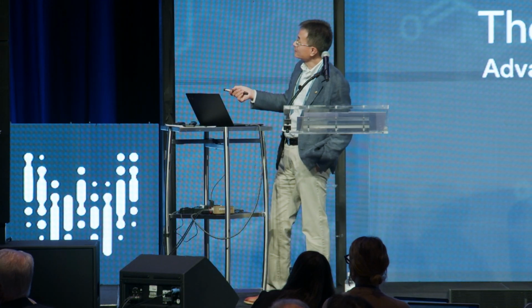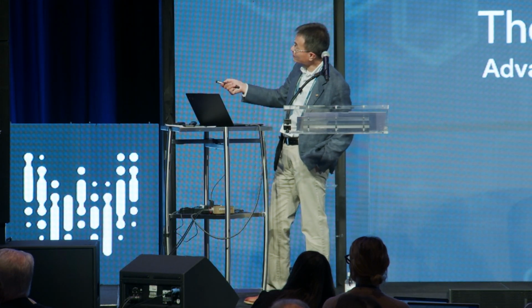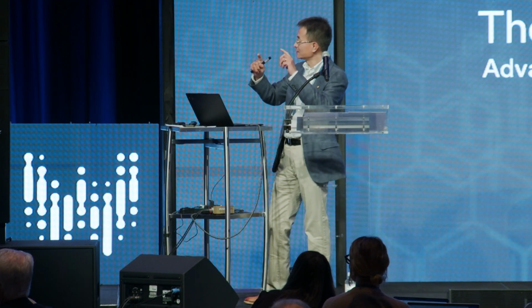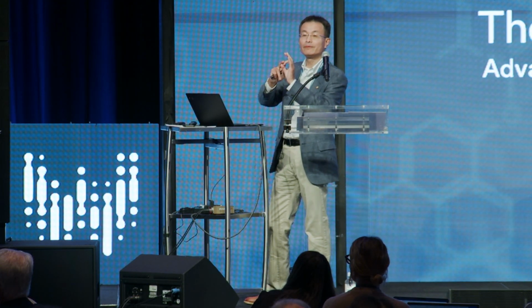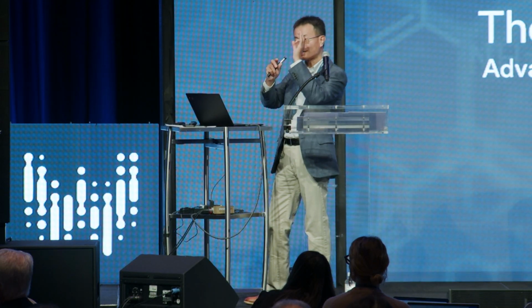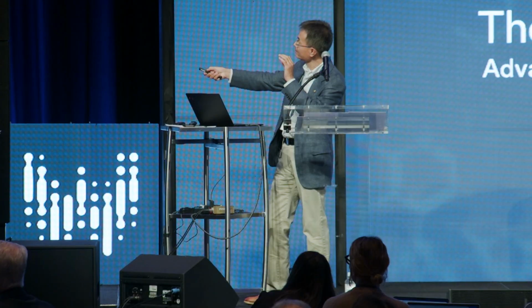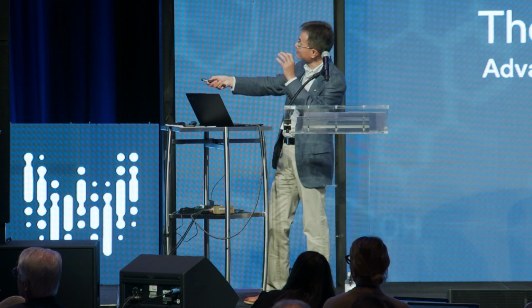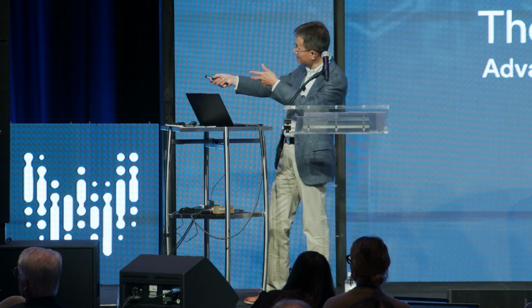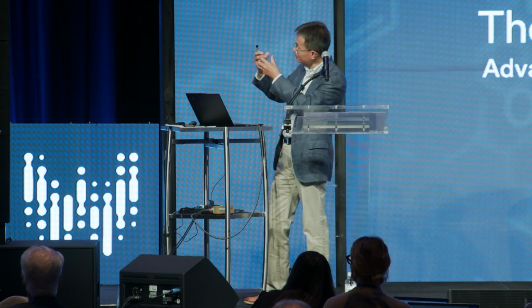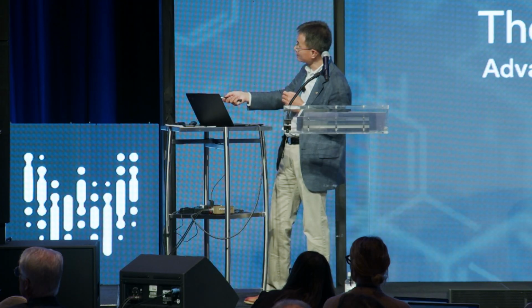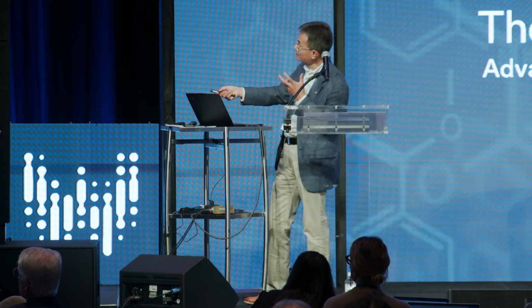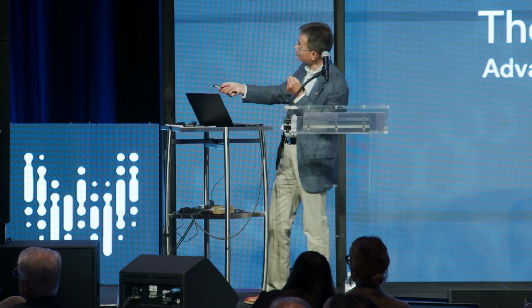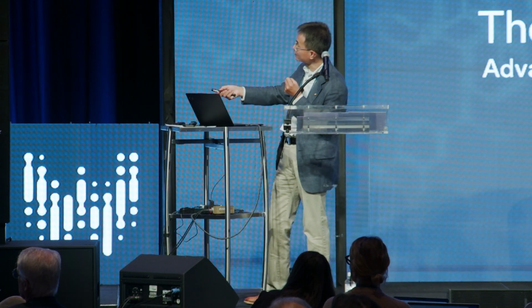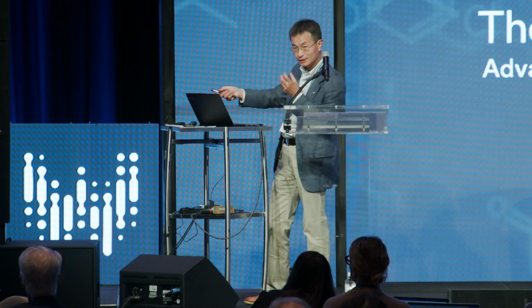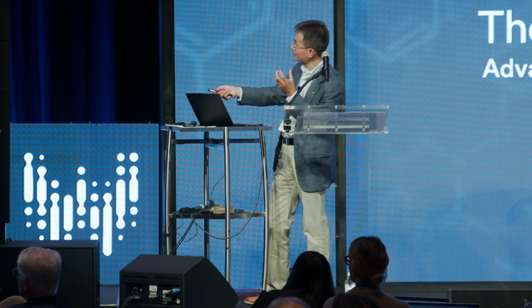Okay, now this is the key. Look at the phase diagram of this so-called eutectic binary system. Gold is our nucleation site, our liquid droplets in this VLS name. Then germanium is supplied as vapor, in this case into the TEM column, and that will start to mix at 800 degrees. If you look at this phase diagram at 800 degrees, as you add more and more germanium vapor, the germanium alloys with gold, and this isothermal line pushes it into this liquid state. That's what the phase diagram tells you. You will see liquid droplet formation.